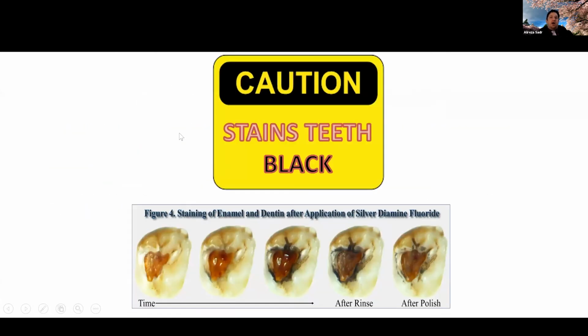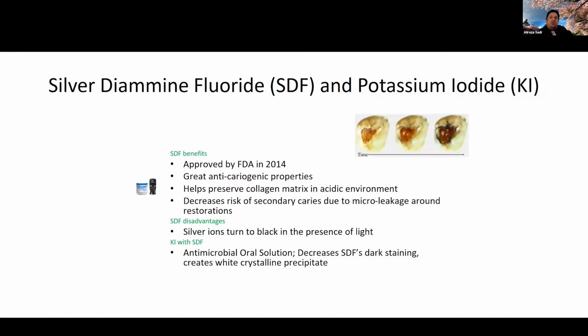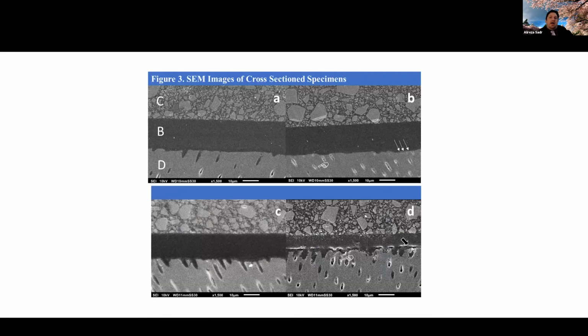Okay, so we talked about the staining, we talked about the application of potassium iodide, and here is a scanning electron microscope looking at the bonded interface. Again, if you're going to bond, as I said, you have to rinse off the SDF after application, even in the glass ionomer or in the bonded interface cases. You don't want precipitation of SDF and especially precipitation of the silver over the dentin surface. So please do wash off SDF after application.